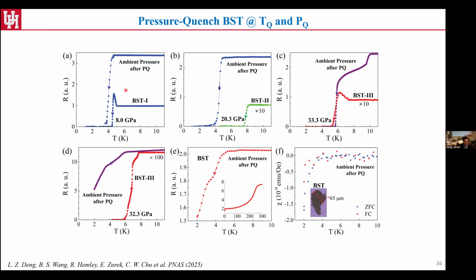And for this sample, something we do further is we spend a lot of effort to recover the sample. I know one of the reasons, when we present our pressure quench work, people often challenge it, or, from a very good view, in case we do some fake experiments, the question asked is this: when you really quench the pressure at low temperature, did you really release all the pressure, or are there some pressure still locked in one way or another, but you are not able to measure or tell? So one clear cut is you just recover the sample from the diamond anvil cell. If the TC is still there, I think it's a very strong proof that we're not trying to hold the 8 GPa pressure, right? That would be too crazy to be true.